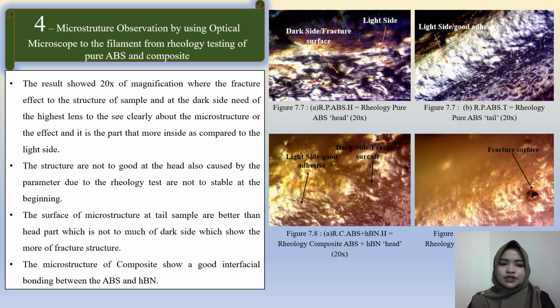The structure is not too good at the head because the rheology test parameters are not stable at the beginning, since at the beginning of the process we need to wait for the perfect parameter that we want. Then the surface of the microstructure at the tail sample is better than the head part, which does not show too much of that. The head shows more fracture structure. Then the microstructure of the composite shows a good interfacial bonding between ABS and HBN.